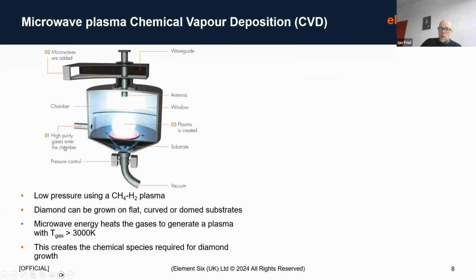Element 6. So unlike the high pressure, high temperature, CVD is a low pressure technique. We use a methane hydrogen plasma, so methane contains carbon. That's our source of carbon for diamond growth. It's a very versatile technique. So with one reactor platform, we can grow on flat substrates, curved dome substrates to produce diamond parts of different shapes. We use microwave energy to heat up our gas mixture in order to form a plasma. The gas temperatures are typically greater than about 3000 Kelvin, and we do this in order to create all of the chemical species required for diamond growth.